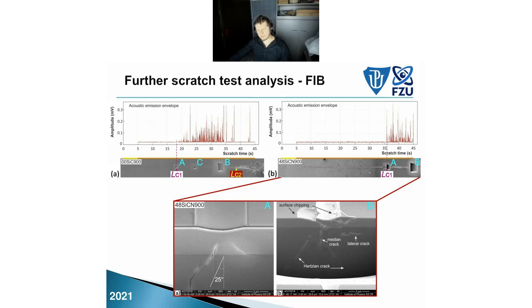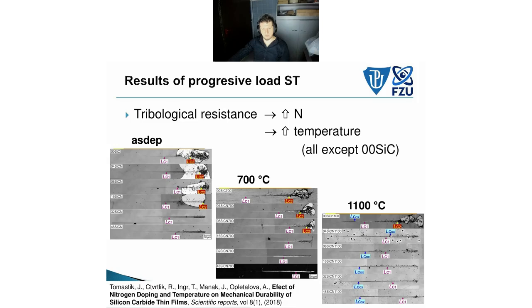This is silicon carbide, so we can see nicely interfacial cracks and cracks from the substrate. So actually, the coating prevailed. The coating was very strong, not so brittle as pure silicon carbide, and we have a nice result. Just quickly to summarize our results, here are the pictures.